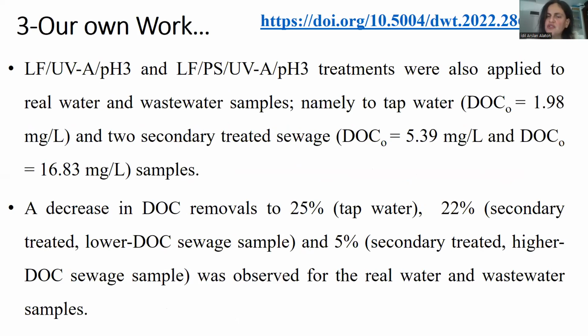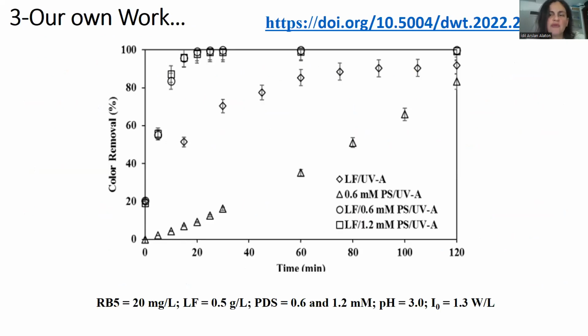We also used as the medium besides tap water, 2 different types of sewage. You see that even treated sewage can change, the composition can change, the concentrations can change. So a decrease in DOC removal was observed from tap water going to the secondary treated higher DOC sewage sample down to 5%, which was expected because here we have a high pollution load coming from the background. You see here, you can compare the photocatalytic treatment, the enhancement with persulfate here, and we have also some control experiment, UVA with PS, which has a completely different kinetic. So even UVA photolysis of PS just brings about some oxidation.